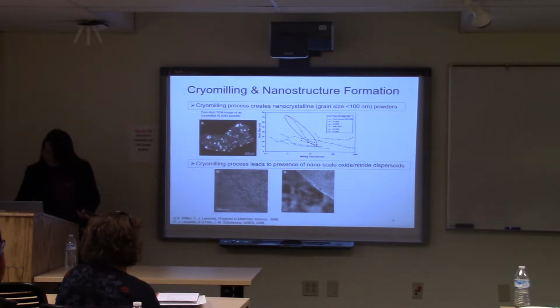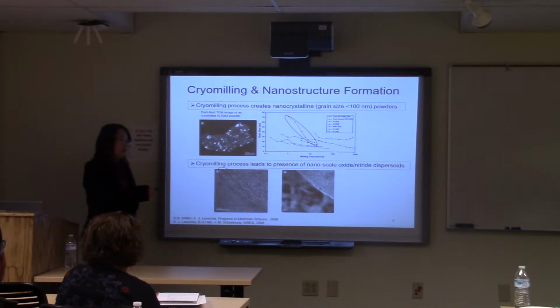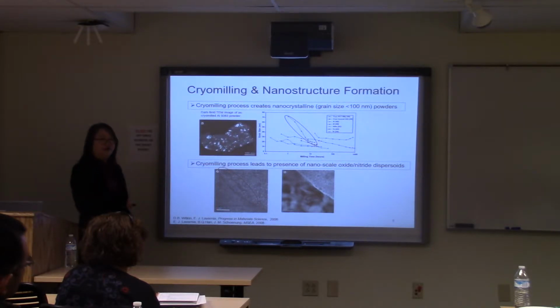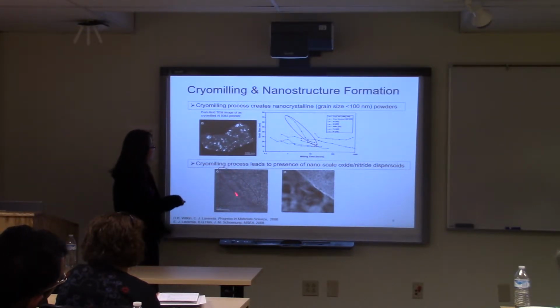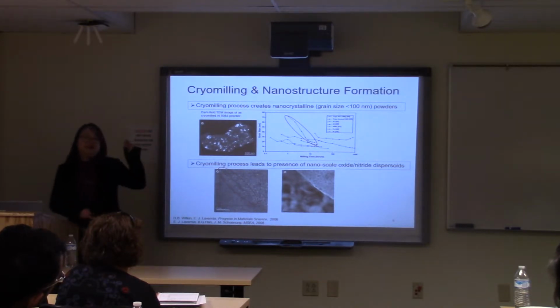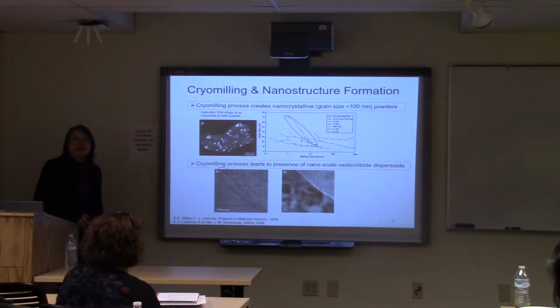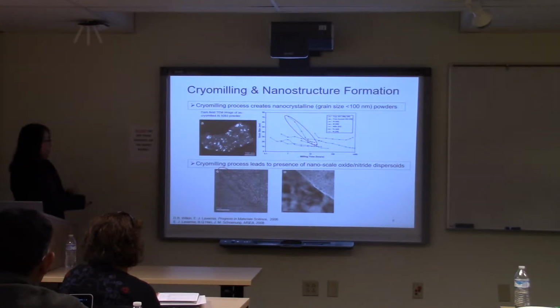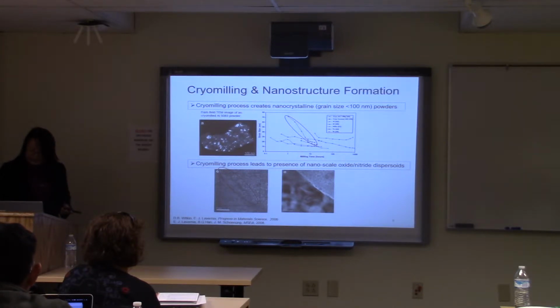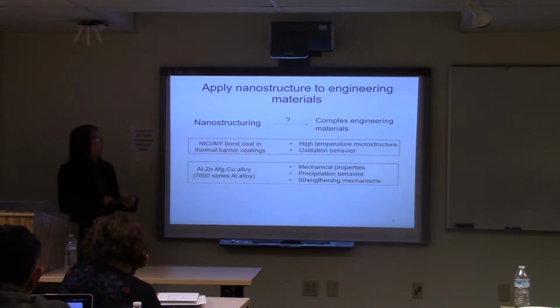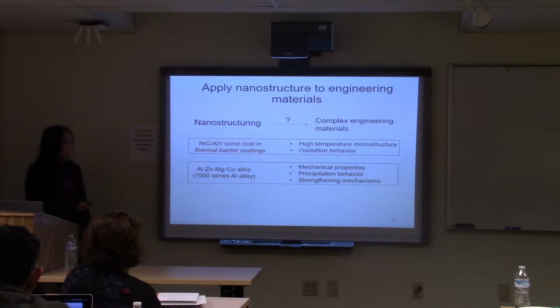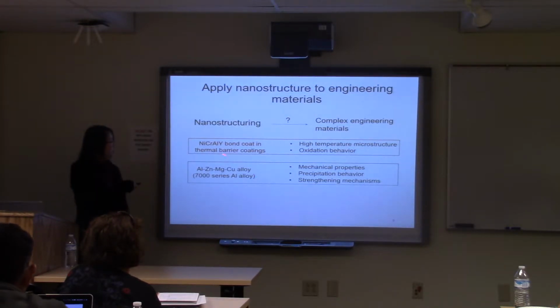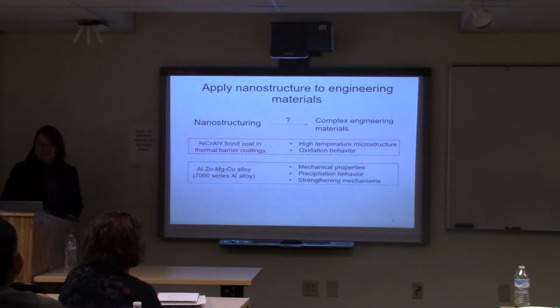What's more interesting is something we didn't expect at the very beginning, but did find. Cryomilling also leads to in-situ formation of nanoscale oxide and nitride dispersoids in the powder. I hope the people in the back can also see this. This is a high-resolution image showing the atom arrangements, and by measuring the distances between them, you can determine which compound or material it is. So these two unique features of cryomilling give the idea that we can apply this method to complex engineering materials too, because we can start with the powder. Now I'm going to move into detail about the bond coat in thermal barrier coatings.